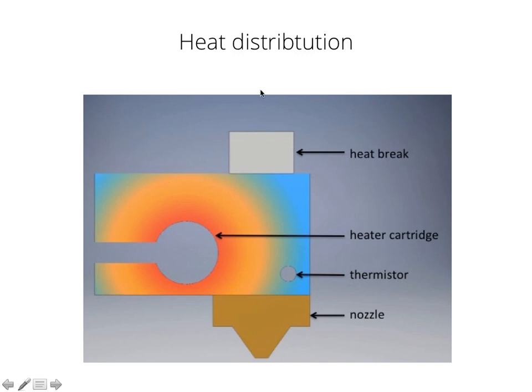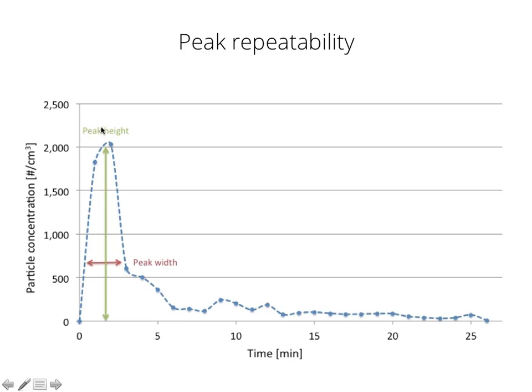So while the filament is still sitting inside here in the heater block and it's being heated, while the heat block heats up, you have an overheated filament in there, and that's why you have this steep increase of particle emission at the beginning, because you have such an overheated polymer being extruded. So this was already a first indicator that the temperature does have an influence on the particle emissions.